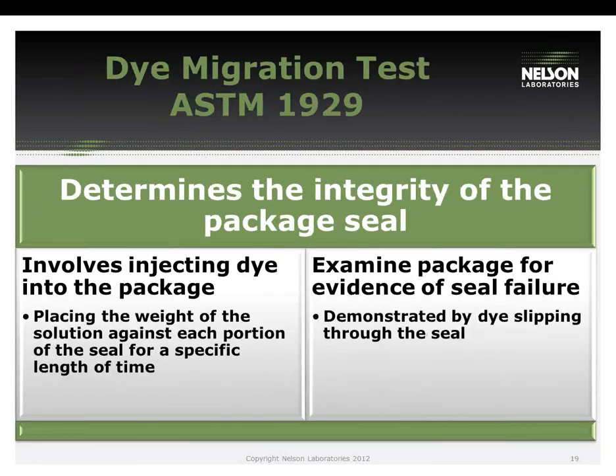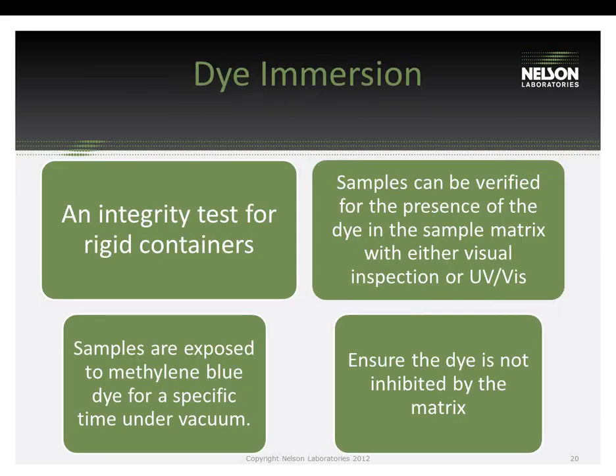The next test we're going to look at is dye migration. Dye migration is the process of injecting dye into the package. We allow the weight of the dye to sit along the seal for a specific amount of time. You have to be careful with this test because the dye can have a wicking effect through porous material. So if you leave the solution in the package too long, you could pick up false failures because the solution actually wicks through the package rather than actually coming through the channel. This is a test for seal failure. It is not a whole package test.